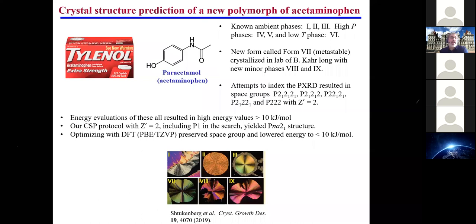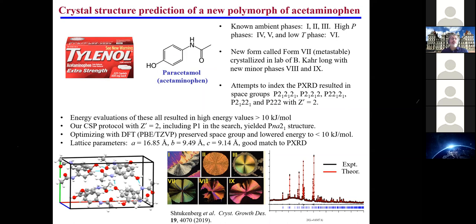And so we turned our CSP protocol loose on this and included searches with Z prime equals 2 and included low symmetry space groups and all of this. And finally, what you get is a Pna21 structure that has a low energy, all right, and a really good match to the powder X-ray diffraction, right? So that's what this thing gives.